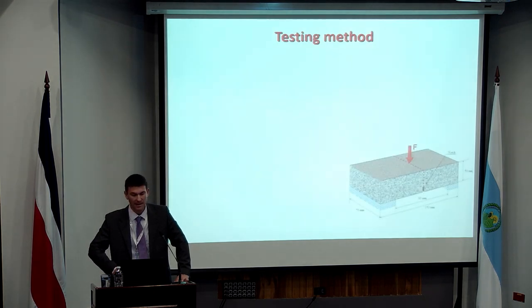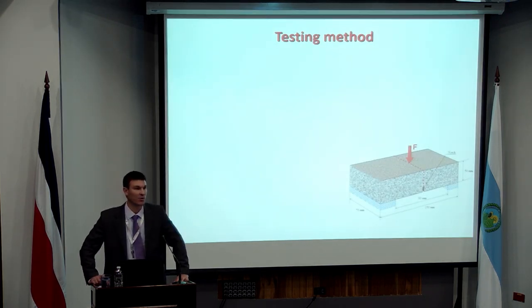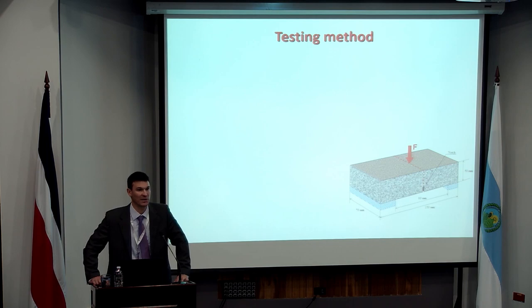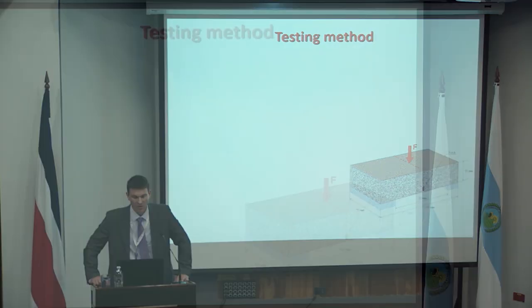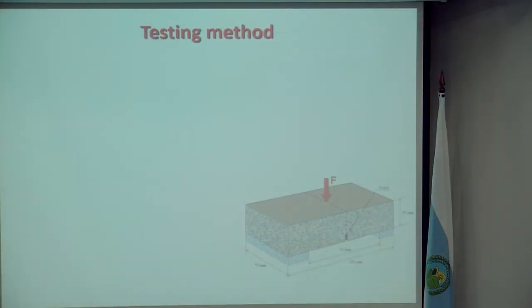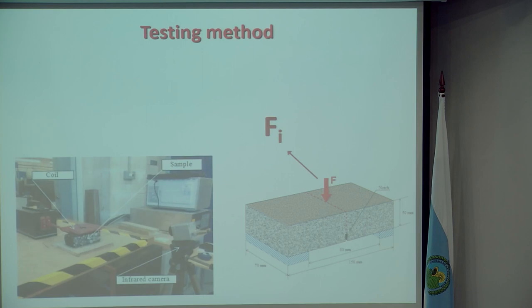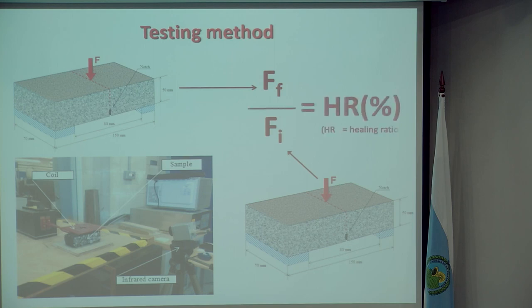How do we quantify that? Well, we quantify it again with that very simple three-point bending test that I talked about at the beginning. You have your specimen, you obviously apply some kind of initial load to work out its initial pre-damage strength. You then give it a value Fi, you put that specimen through the induction heating process. You test it again using your three-point bending approach to get another fracture strength, call that Ff, and you determine that healing ratio. How successful is it?